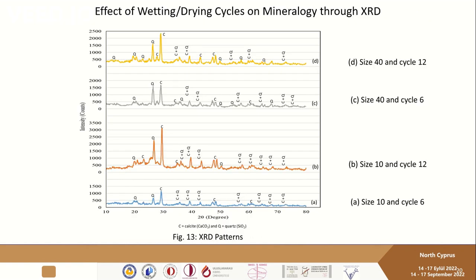Also, if you consider the effect of wetting drying cycles on mineralogy through XRD, we can see that the main two peaks were quartz and calcite, and these peaks were getting increased by subjecting the samples to more cycles. But these peaks were higher in the case of samples containing PET shreds of size number 10.